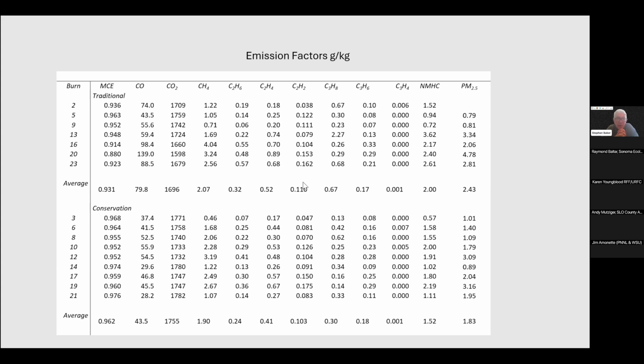Although the methane emission factors were pretty similar, most of the other emission factors that we have displayed for C2 and C3 compounds were lower in the conservation burns than the traditional, which is reflected in the non-methane hydrocarbon sum total, NMHC, which you see there, 2.0 versus 1.52.